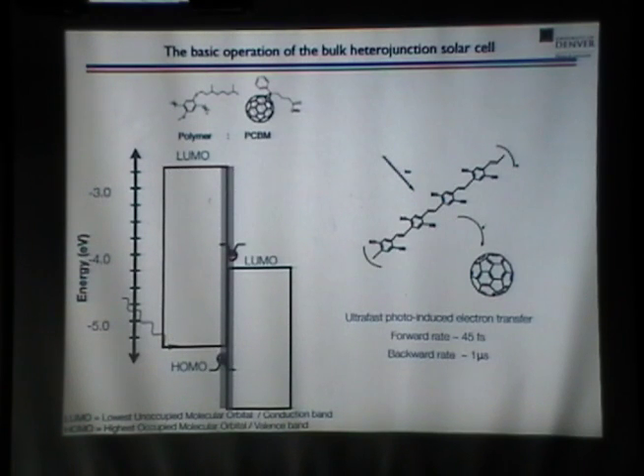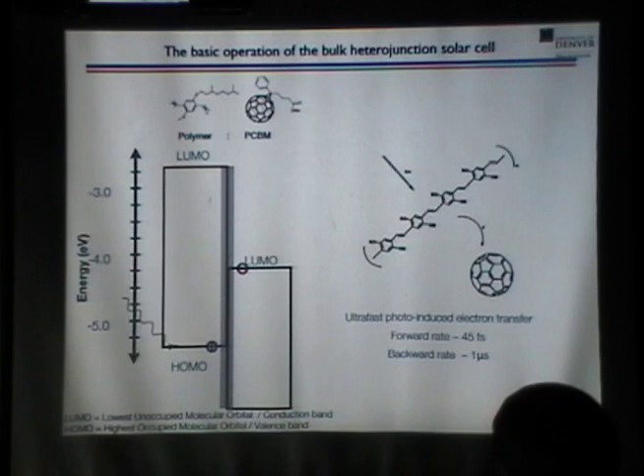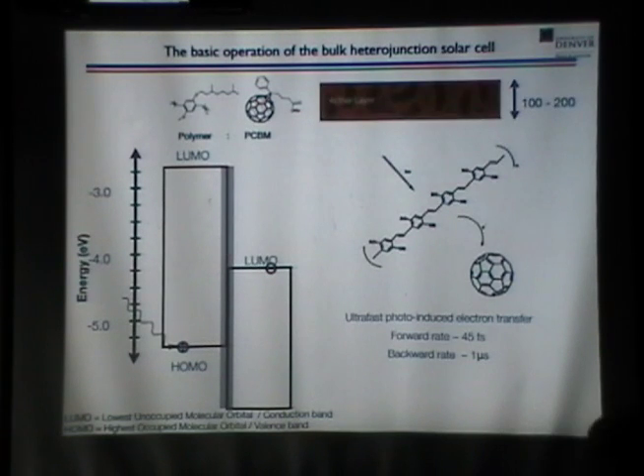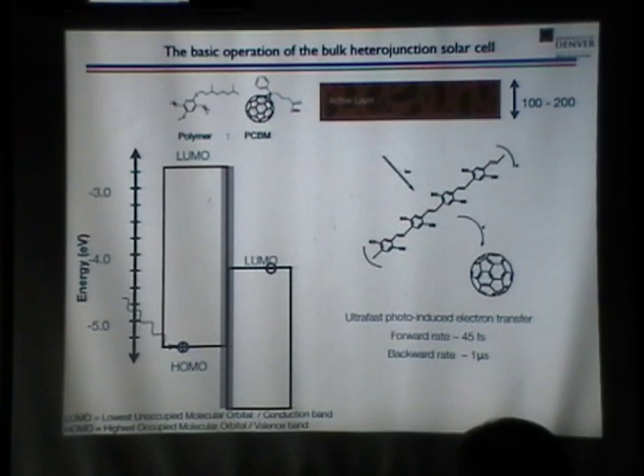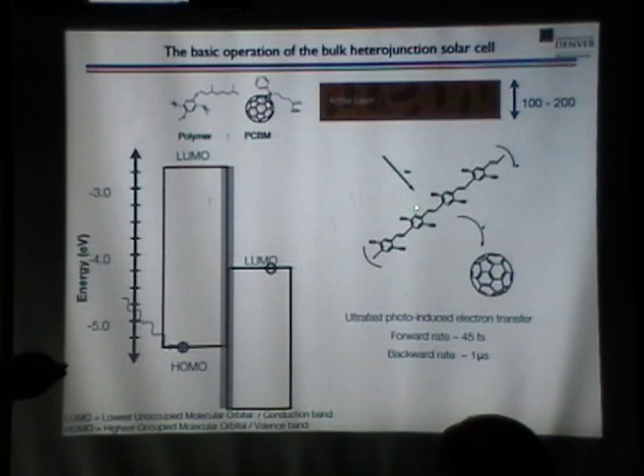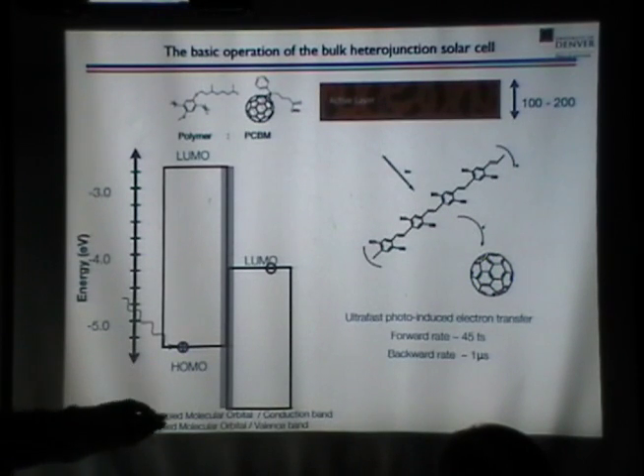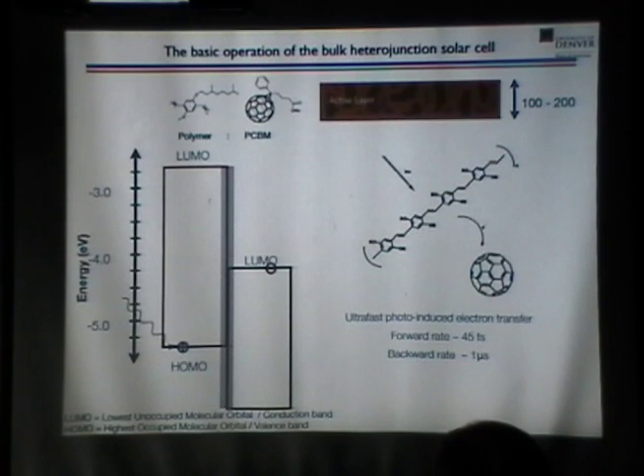But if we diffuse that exciton to the interface, we can transport the electron across the interface, and we'll talk about that in a moment. And then we have the hole on one side of the mixture and the electron on the other, and then through both diffusion and drift, we can drive them away. So this process of charge transfer happens on a very fast time scale. In fact, it's called ultrafast. And it's been measured around 45 femtoseconds for the polymer electrons being injected into the fullerene. This actually competes with natural photosynthesis. In natural photosynthesis, you would get charge transfer rates of 100 to a couple hundred femtoseconds. So this is actually faster than most natural photosynthetic processes.